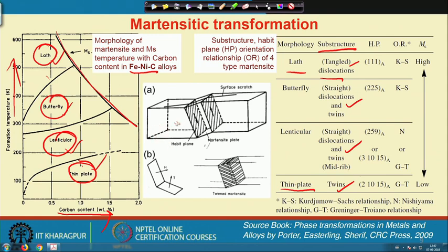Now, if we think schematically that this is the austenite and this is the product martensite, then this is the plane which is the interface between austenite and martensite, which remains unrotated and undistorted, and is called the habit plane. The habit plane could be different in the case of lath, butterfly, lenticular or thin plate. So, this is the direction of the habit plane actually. Or this martensite could have a substructure of twins or dislocations. So, many different substructures appear, and the strain energy can change the morphology of the martensite from a lath to lenticular to thin plate and so on. The higher temperature and the lower temperature are involved with these 4 types of transformation.